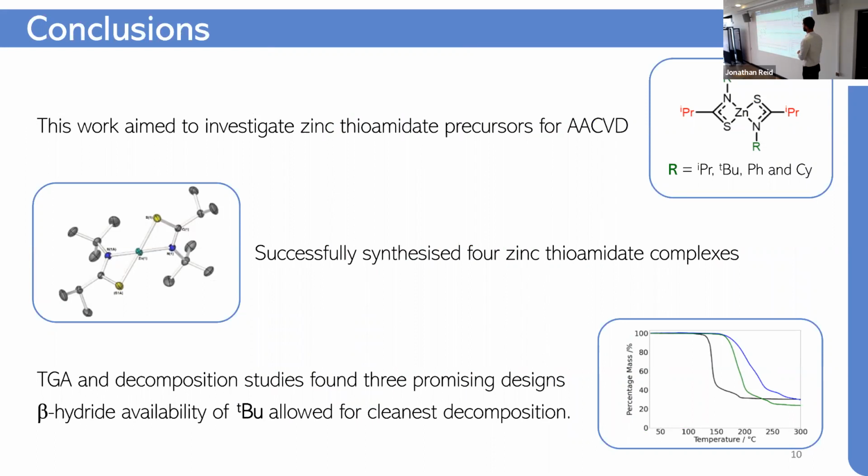So this work aimed to investigate zinc thioamidates as potential precursors for aerosol-assisted chemical vapor deposition. I managed to successfully synthesize 4 of these that I designed, and doing some thorough analysis and some decomposition studies, found 3 promising designs, one of which had a really nice clean decomposition because of the availability of beta hydride of the tertiary butyl group. So, bringing this forward,